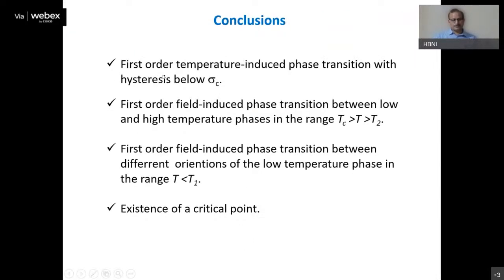points: first order temperature induced phase transition with hysteresis below some critical value of external field, and then first order field induced phase transition between low and high temperature phase in the range between the critical temperature and some T2 temperature, which is one of the spinodal temperatures, and then first order field induced phase transition between different orientations of the low temperature phase in the range less than T1.